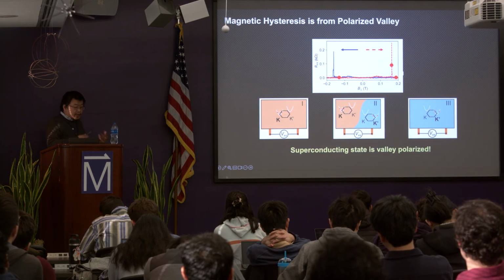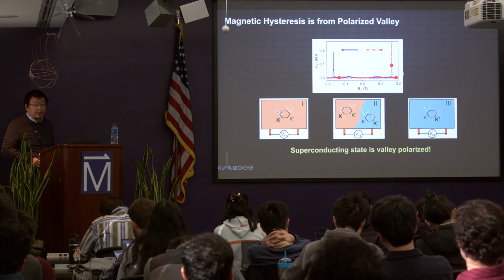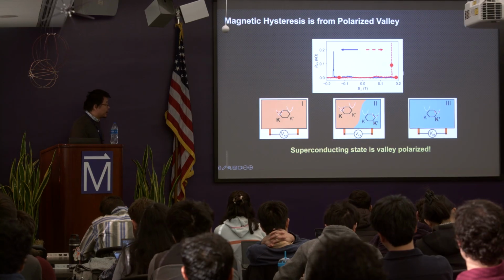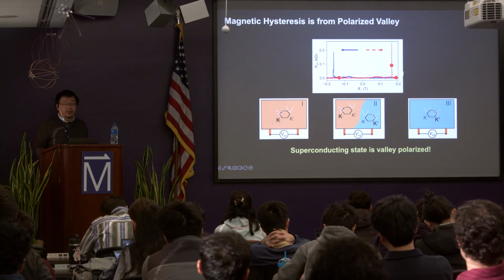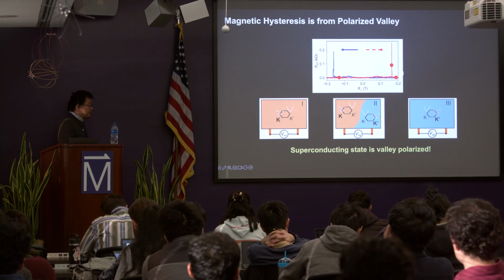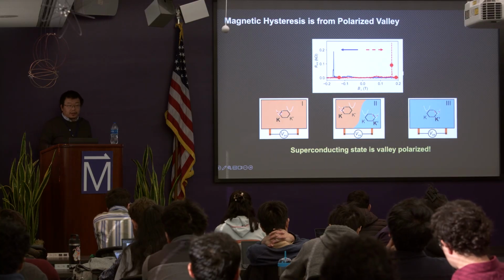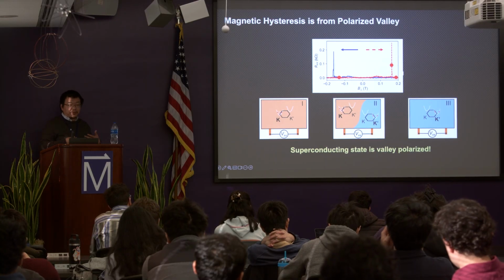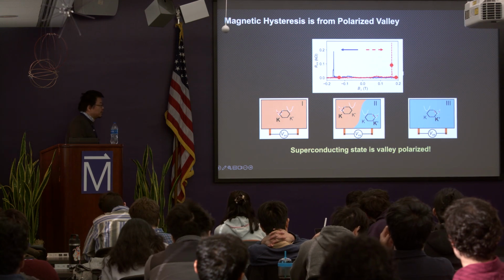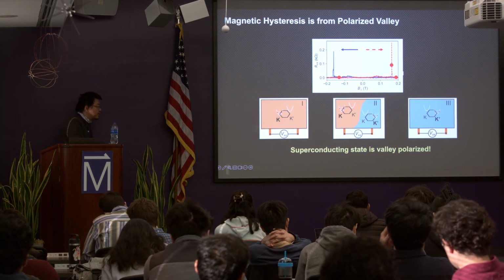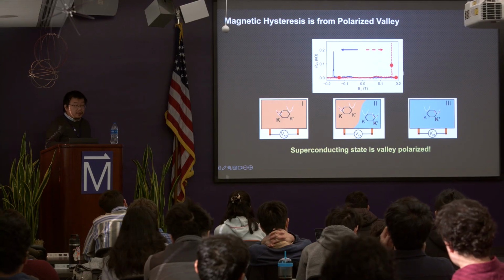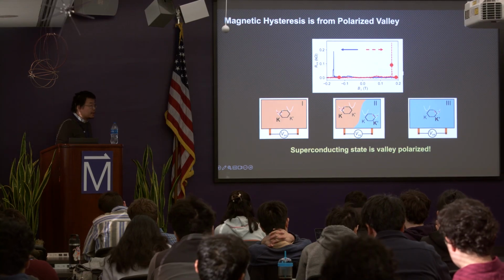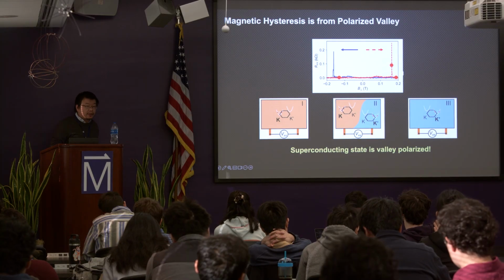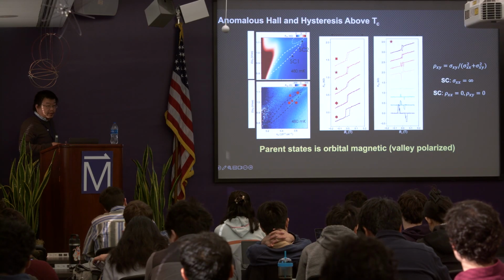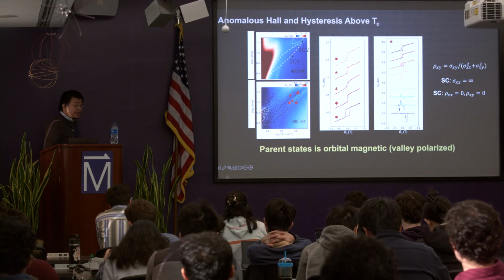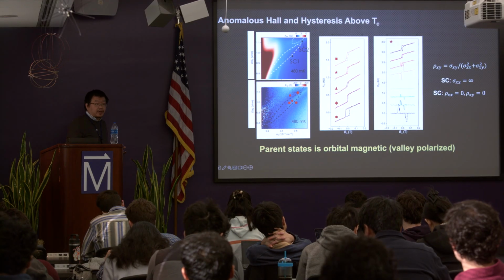So this is something like a hand-waving picture we have. If you think about this superconductivity pairing as within one valley, then you can have different kinds of domain walls at zero magnetic field because it does not know to prefer K or K prime. If you have a domain wall that propagates throughout the sample, when you sweep the magnetic field, this will cause a jump of the resistivity, and when you push it back, it has a jump on the other side. Of course, this is just a guess. So you need to give more evidence for why I say the pairing should come from a single valley.